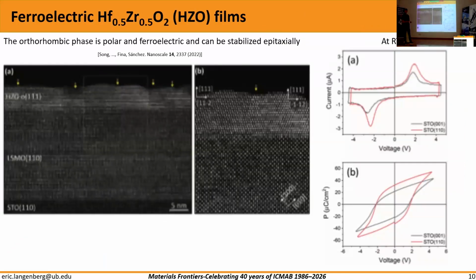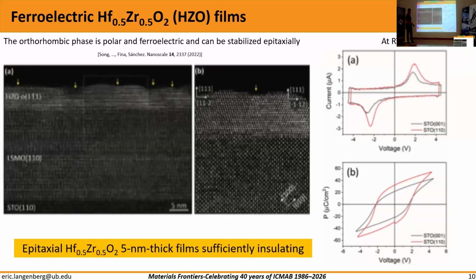This is hafnium zirconium oxide. This is actually a report here at ICMAB by Fina and Francesc Sánchez on hafnium oxide. And they can be very, very insulating even in 5 nanometer films. So that's why we moved to hafnium oxide, to have the possibility to apply electric fields and change the domain walls in a ferroelectric material that is very, very thin.